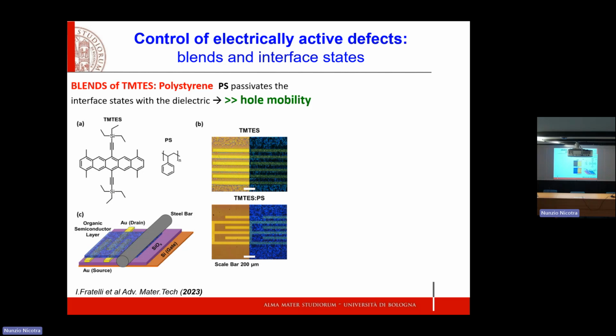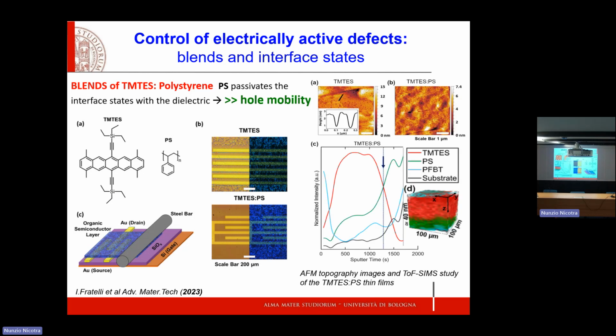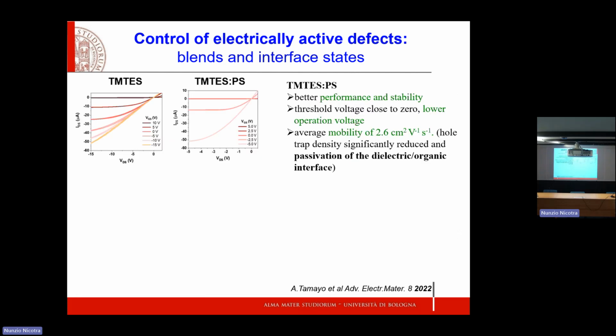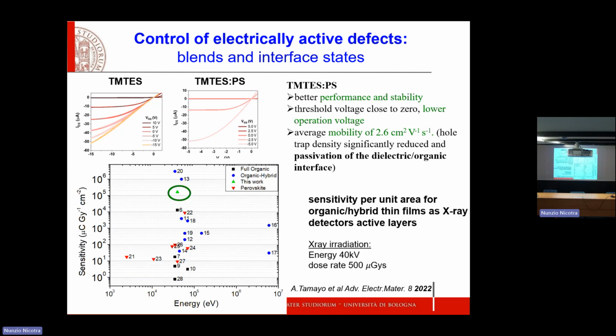You can see the optical image. In the optical image, I'm showing you the difference between a pure TMTES film and a blended film. Why am I doing this? Because we noticed that this blend is not really homogeneously distributed throughout the film, even if the film is really thin, a few hundred nanometers, but polystyrene tends to segregate at the bottom interface. And this is not a negative thing because it helps passivating all the interface trap states that are located at the bottom interface. Thanks to this passivation that you achieve simply by doing the blend together, you clearly see that the mobility of the blended polymer is much higher.